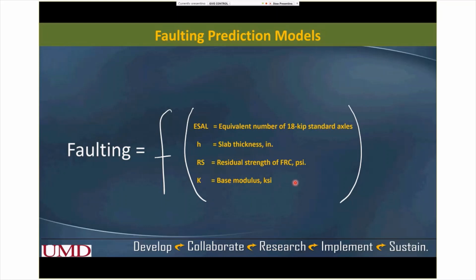Here we try to relate the measured faulting with respect to ESALs, slab thickness, residual strength, and base modulus. For the base modulus we didn't have any test data, but we found other research work conducted at MnROAD where they reported either resilient modulus or other parameters. So we used those to get K, and we also got the K with respect to different seasons.